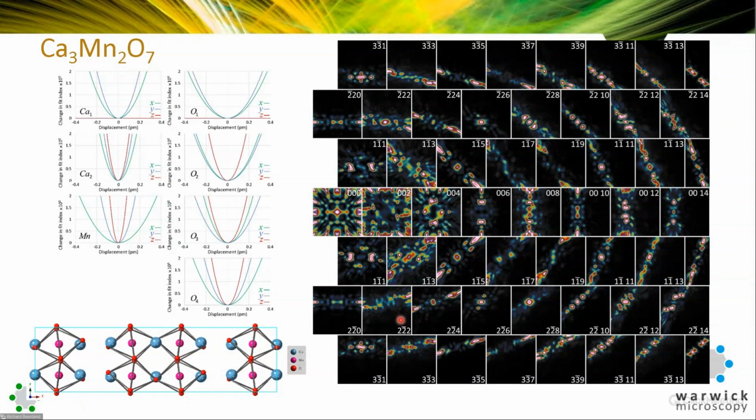So I suspect, again, this is due to charge transfer between the atoms. In fact, if I refine the occupancy in this material, I get the oxygen occupancy always goes down to about 95%, which physically isn't reasonable. There's no way there's 5% oxygen vacancies here. And the calcium and manganese always goes over 100%. So this must be due to charge transfer.